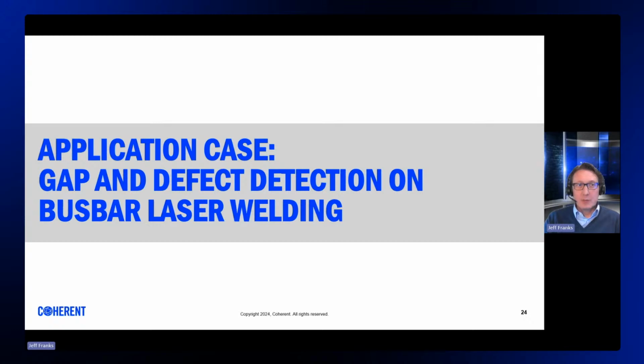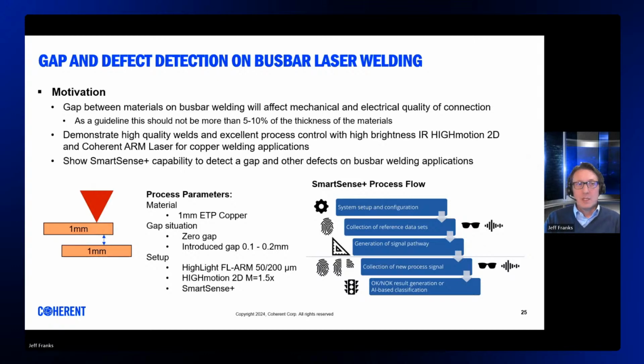For the last section, I would like to examine a case study demonstrating how these modern packages work together in unison to bring value to customers. We selected some typical copper material to weld in a generic overlap busbar configuration with our highlight FL-arm and high motion 2D package, and introduce increasing gaps or gap faults in the range of 0.1 to 0.2 millimeters to the part setup to demonstrate how the SmartSense Plus process monitoring would track and classify the weld results.